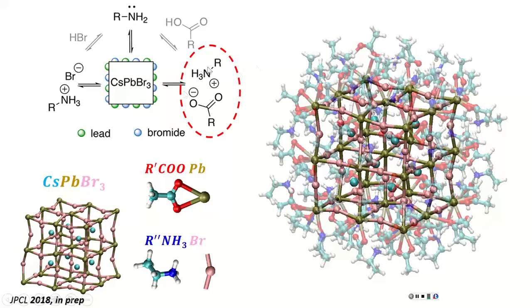And that's this slide here. So you can see this ligand combination we use to passivate a lead halide perovskite nanocrystal, where the inside is made up of a 2x2x2 unit cell, which is about 1 nanometer wide, for a perovskite quantum dot. And then for all the surface leads, there are these small chain acids. I guess you could call it a formic acid, or it is formate if it is without the proton. Formate, yeah, so it's the charged ligand. Oh, it's not formate, it's acetate in your work. Acetate, yeah. So an acetate anion binds to the surface leads.